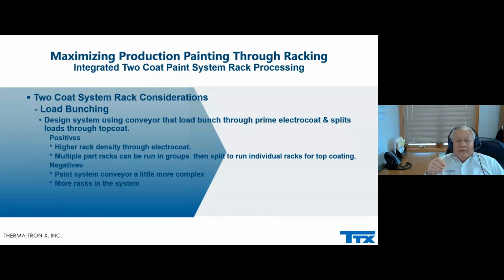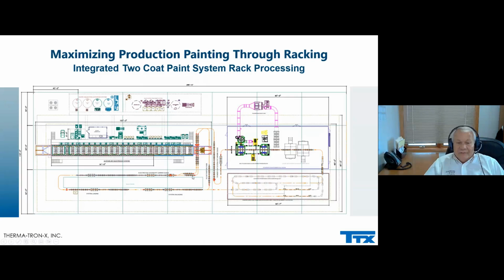If we look at integrating the two-coat paint system rack processing, we could do what we call load bunching. You design the system using a conveyor that load bunches through prime electrocoat and splits the loads through top coat. The positive is higher rack density through E-coat. Multiple racks can be run in groups, then split individually for top coating. The negatives are the paint system conveyor is a little more complex, and there are more racks in the system.